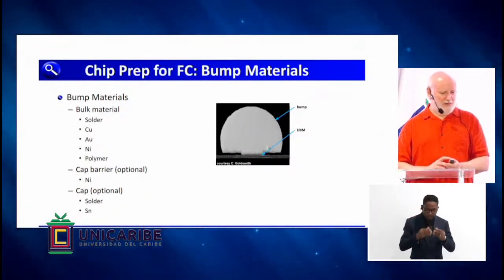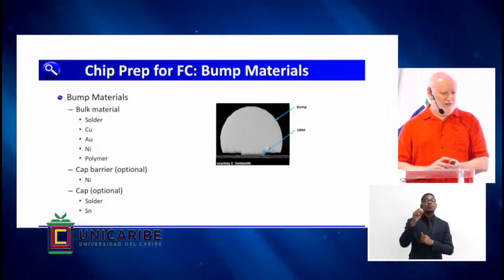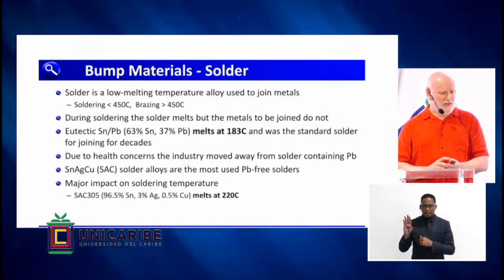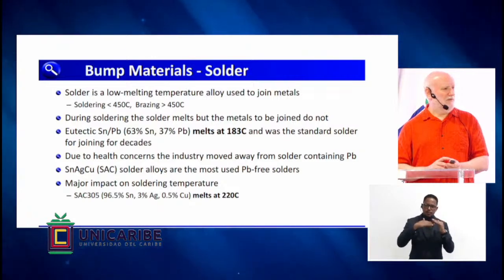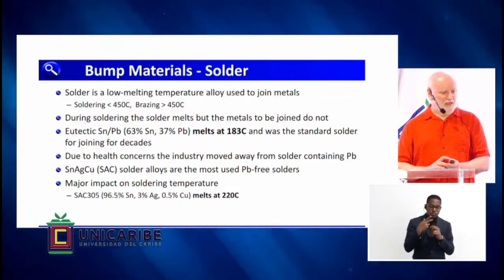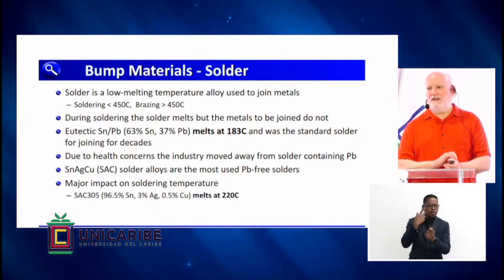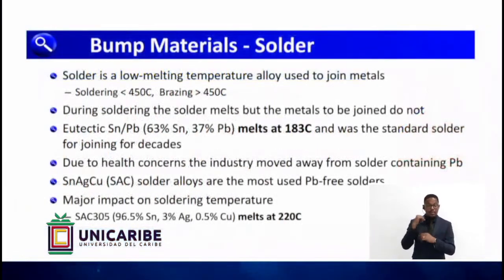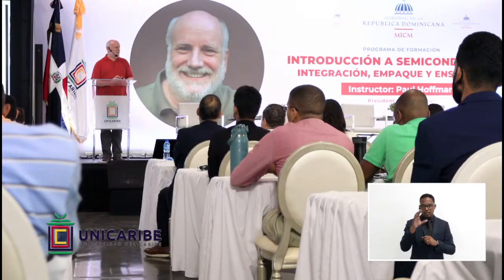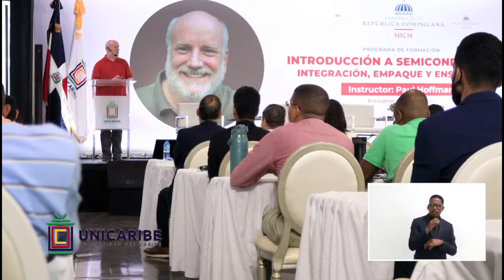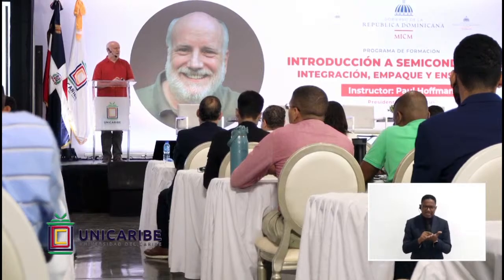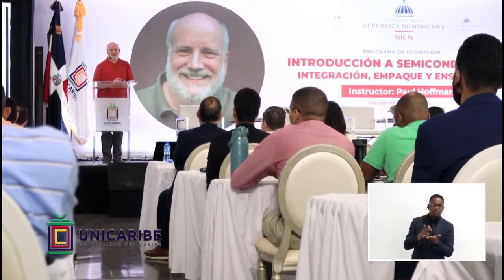So above the UBM is the bump, and different materials have been used for that over time. Solder has been for a long time one of the common bumping materials. Originally, we used to use something called eutectic solder that melted at 183, but because of the desire to get lead out of electronics, the industry has gone to something called SAC, or tin, silver, copper solder, which has impacted us in the packaging world because the melting temperature is quite a bit higher. It's 220 C, so we had to adjust all our assembly processes when that change took place.